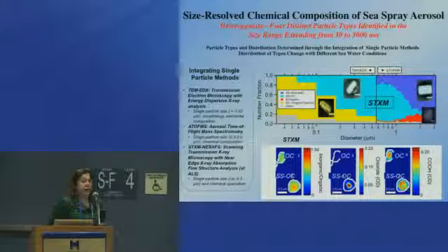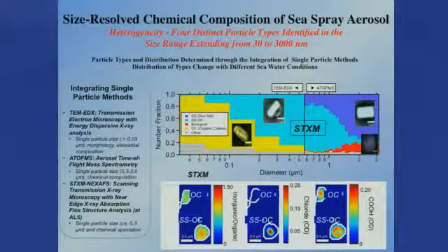So we integrated a number of different methods, and we were able to give you more idea of the chemical composition of sea spray aerosol from 30 nanometers to 3 micrometers. Even though on an individual particle level there are differences, we tried to get a fuller picture besides just sodium chloride in this first stab at understanding these particles. We integrated aerosol time of flight mass spectrometry data with transmission electron microscopy, energy dispersive X-ray analysis. We had a glue that stuck this all together called STXM, scanning transmission X-ray microscopy, done by Ryan Moffet, and here's some of his data.